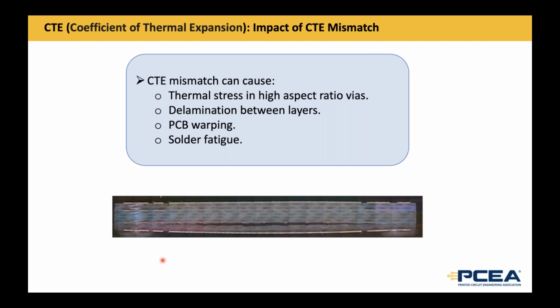Tony, did you want to add a little bit to this? And since you actually found this cross-section image for me, some examples, stories about what other problems can occur with CTE mismatch? Well, there are a lot of things that relate to CTE mismatch. You described a few of them. We could be here months talking about it. But this particular picture is from a test that was done to differentiate materials that were made with two different types of material. And you might be able to see in the picture the 4 layers of copper. And this is a simple 4-layer structure that was designed to evaluate resistance to delamination in a hybrid structure.